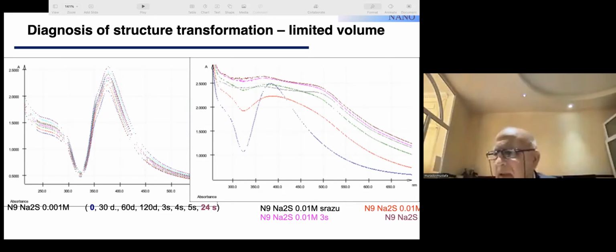And we showed that when we increase the concentration, the wire structure is destroyed, and we get silver sulfide nanoparticles. Here we also showed the process of transformation of structure from the time of the modification process.